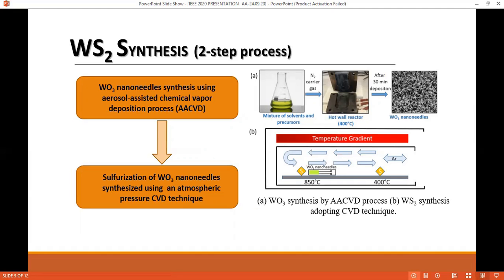The duration of the whole process was 30 minutes, and after the deposition, the sample was annealed at a temperature of 500 degrees Celsius in synthetic air. In the second step, tungsten disulfide was synthesized by the sulfurization of the grown tungsten trioxide nanomaterial using an atmospheric pressure CVD technique.